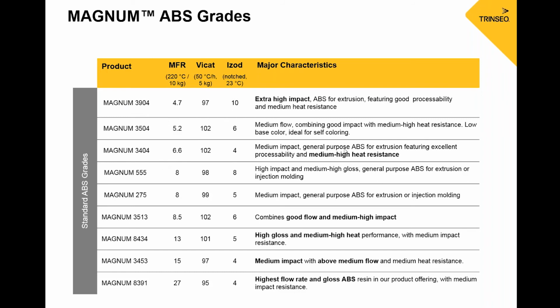So we have a wide range of gloss values. Like I mentioned before, we're able to fine tune the process. So we have low gloss products, we have medium gloss products, and we have some products like this Magnum 8391, which is the highest gloss product that we have, that can get up to around 90. And when we talk about gloss, that can be a result from the processing itself. So there are some adjustments that you can make in your process to lower or increase the gloss level. So important to consider as well.